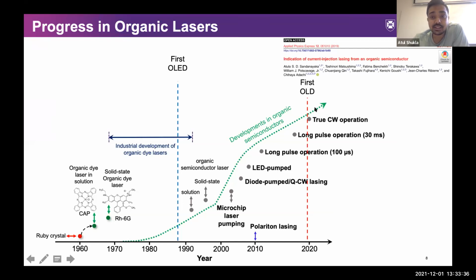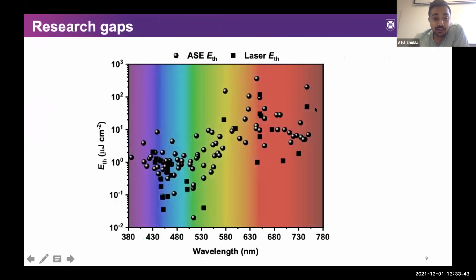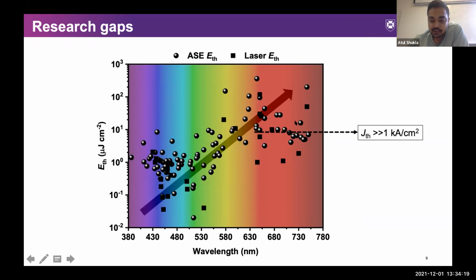But even after such comprehensive developments, there are significant research gaps. One of the major things is that when we plot the ASE and laser thresholds for organic semiconductors as a function of wavelength, we clearly see an increase in threshold with longer wavelengths. That is mainly because of increased non-radiative losses, as well as aggregation induced quenching for materials emitting especially in the red regime. If we take an average of these values and get a rough estimate of the current density required to achieve these thresholds, we find that the current densities are much higher than 1 kiloampere.